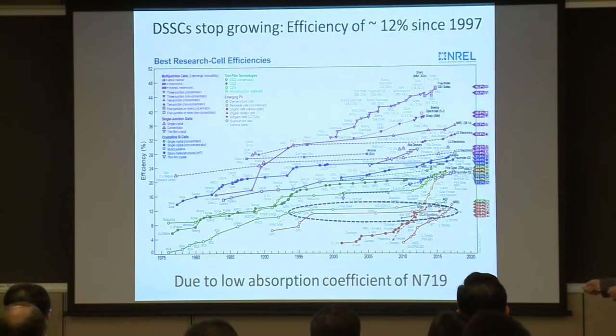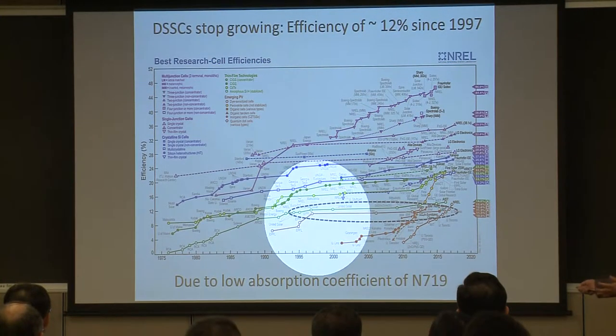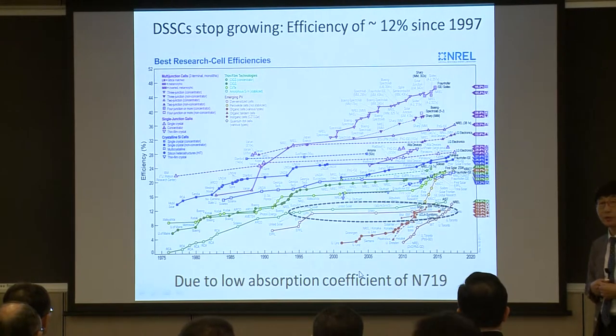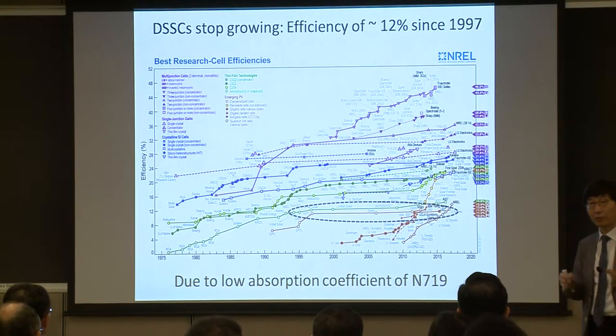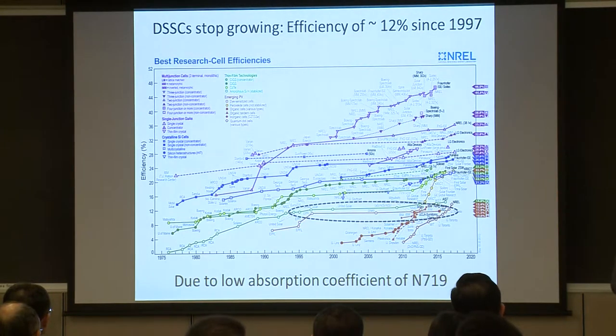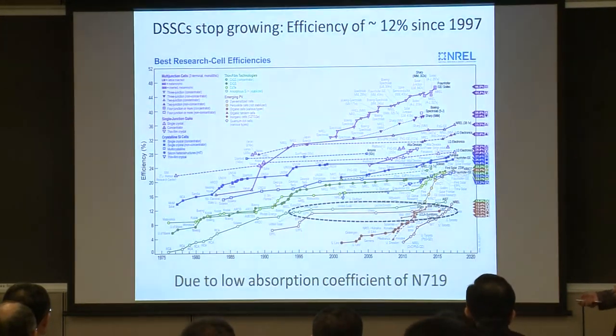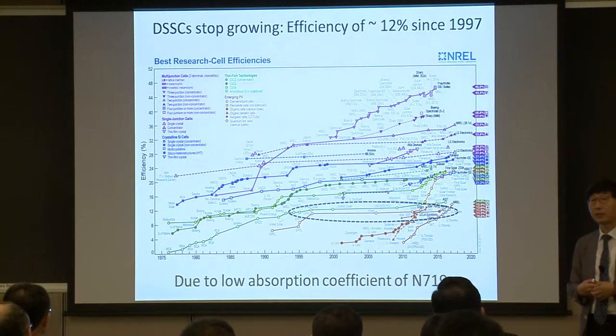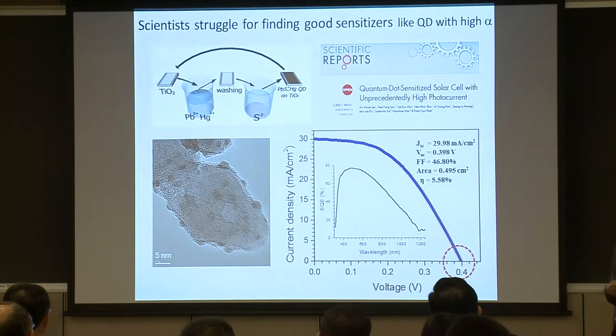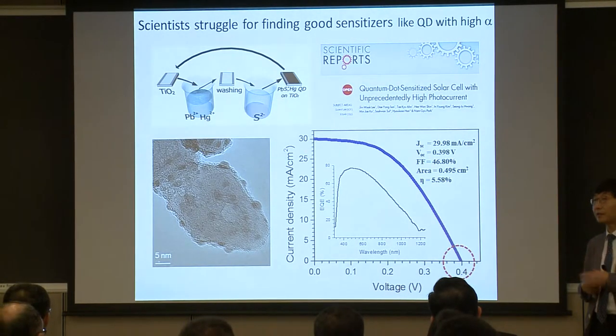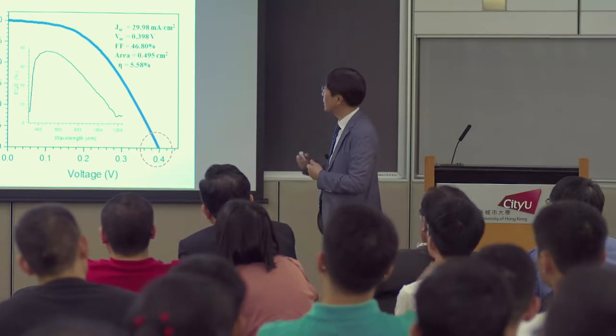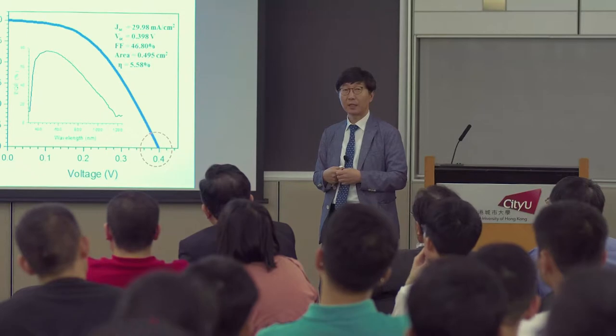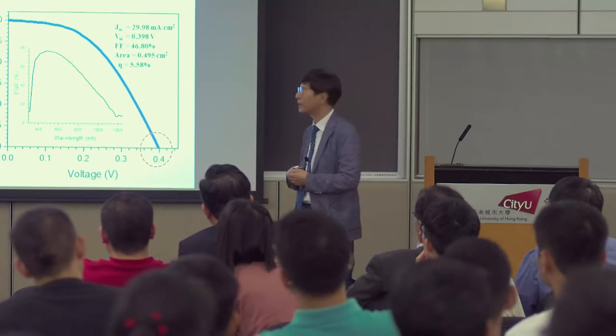But the problem you see here is that the dye-sensitized solar cell's efficiency was always saturated for a long time. Over 20 years, the maximum efficiency was about 12%. So people working on the dye-sensitized solar cell would like to search for some new material, because this is due to the low absorption coefficient of the ruthenium-based sensitizer. So people would like to find a new sensitizer. And at that time, one transient state in dye-sensitized solar cells was to seek the quantum dot, because quantum dots have a higher absorption coefficient than organic sensitizers.